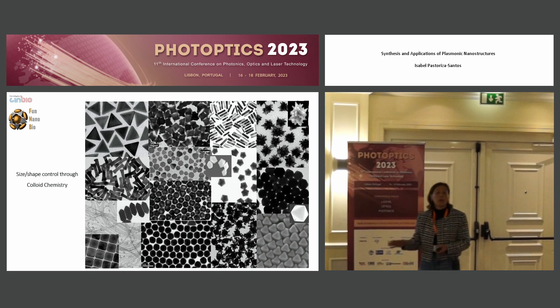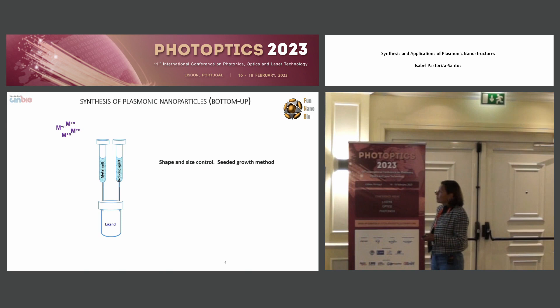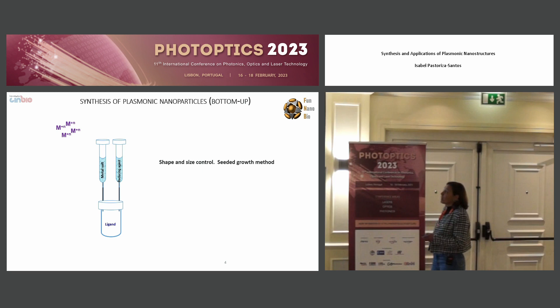Using chemical procedures, we are able to modulate the size and the shape of nanoparticles. Just to let you know, because most of you are probably physicists, we use a chemical reduction method that involves the reduction of a metal precursor with a reducing agent that gives electrons to the metal precursor in the presence of a ligand that provides chemical stability.